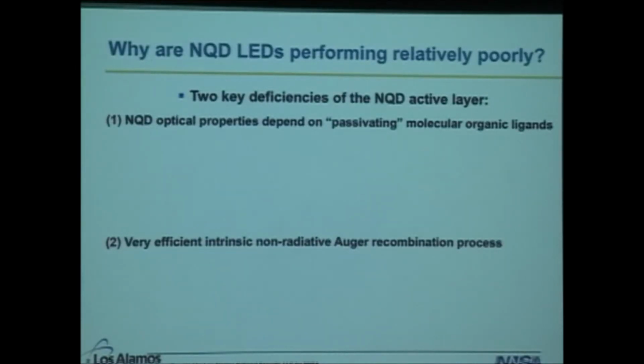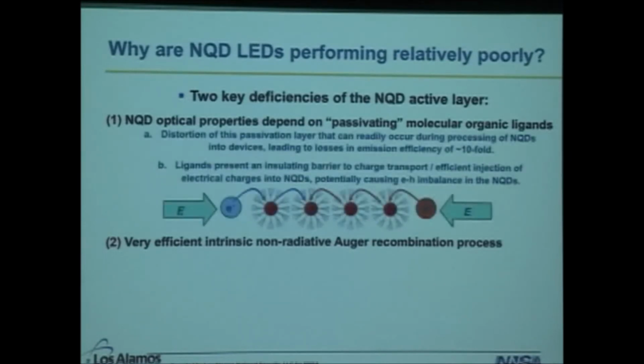So there's an obvious question: why are NQD LEDs performing relatively poorly to date, with all their promise? We and others point to two key deficiencies of the quantum dot active layer. The first is that, as I've already alluded to, quantum dot optical properties in the case of conventional nanoparticles depend on their passivating molecular organic ligand layer. When you process the quantum dots into the solid state, these organic ligands can become damaged. They can separate from the quantum dot surface, or, more importantly, under optical excitation they can become damaged, oxidized, and so forth. Anything that can deleteriously affect the organic ligands or their interaction with the quantum dot surface can suppress emission from the quantum dots.